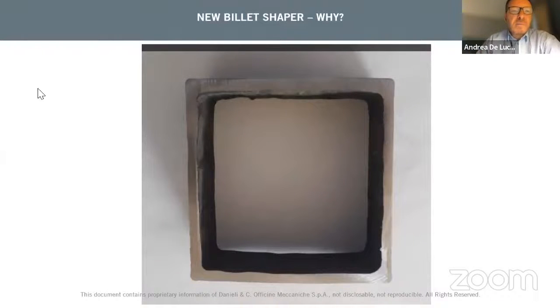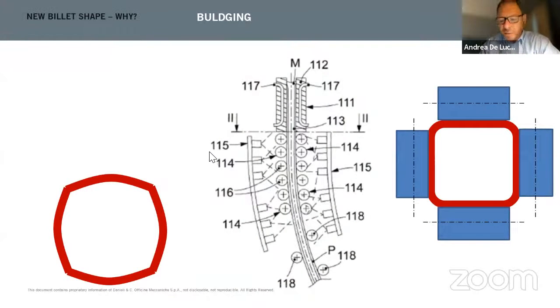So just to give you some details of the Octocaster. Why Octocaster? In conventional casting technology, for high speed, let's say not for quality but for commercial steel applications, the square is the standard shape. But increasing the casting speed and reducing the thickness of the shell at the exit of the caster bring some problems. One of these is the bulging phenomenon. The liquid steel inside the solidified shell gives a pressure and deforms the billet.